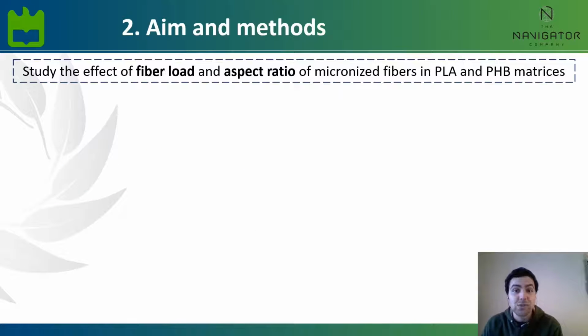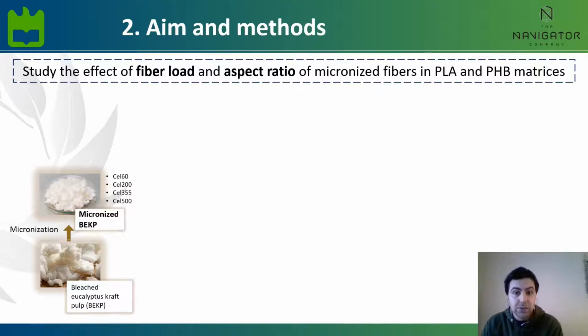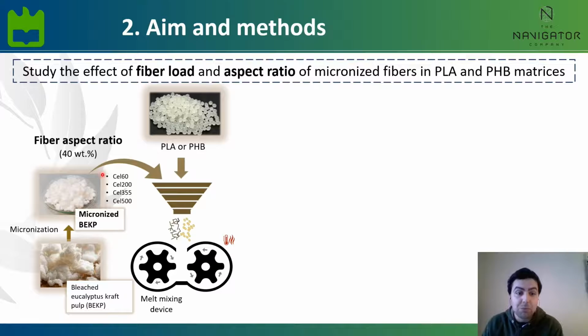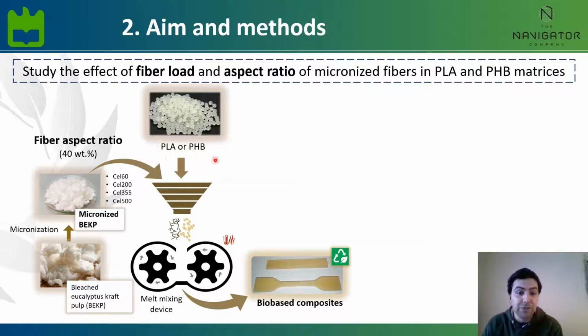With that said, the aim of this work was to study the effect of the fiber load and the influence of the aspect ratio of micronized fibers in the matrices of PLA and PHB. To study the influence of the aspect ratio, we took bleached eucalyptus kraft pulp and used a micronization procedure to prepare micronized fibers having 4 different aspect ratios, and those are cellulose 60, 200, 355, and 500. These 4 micronized fibers and the non-treated bleached eucalyptus kraft pulp were melt compounded with 2 different grades of PLA and 2 different grades of PHB for a fixed fiber load of 40%.